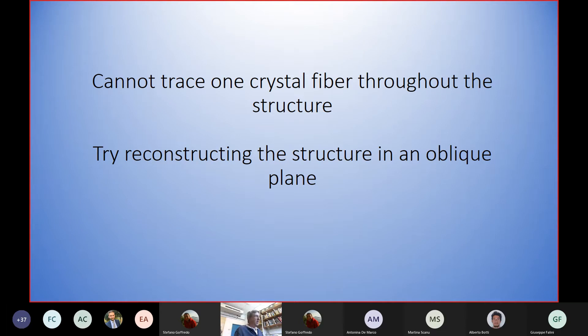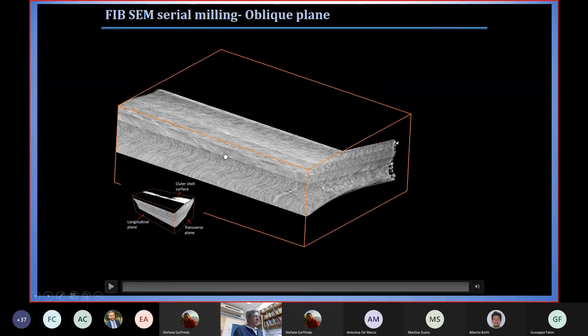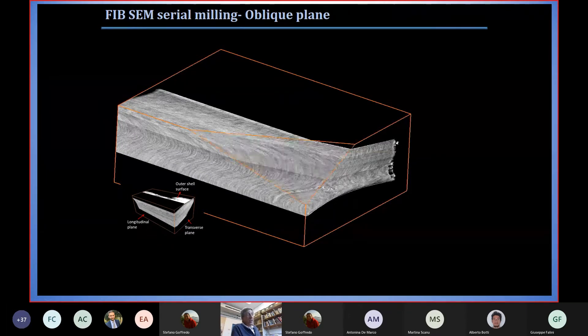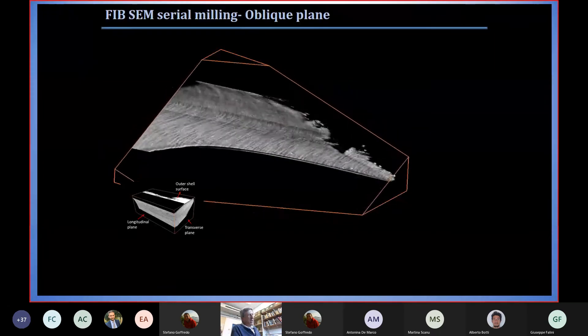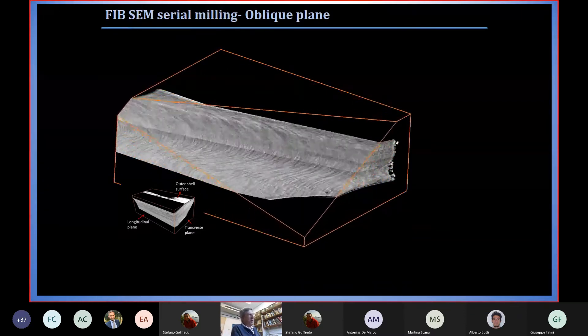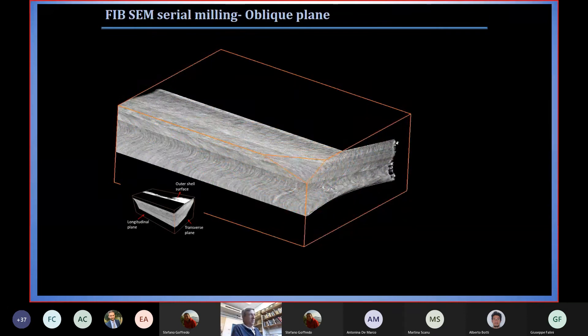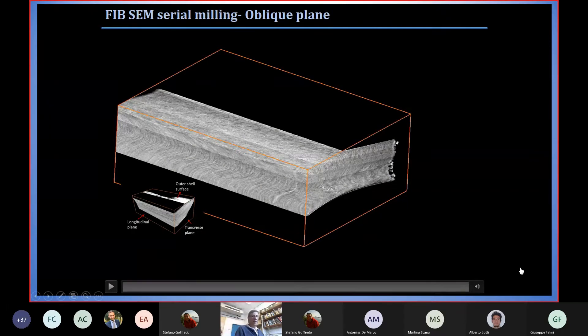We sliced through the oblique plane — the plane from the growing edge to the tip of the shell. In the longitudinal plane, the structure doesn't change as we go through it. That would not be the case if this were a helix viewed from the side. Something doesn't add up, and even with contrast enhancement and edge enhancement, we could not trace one crystal through the plane continuously.